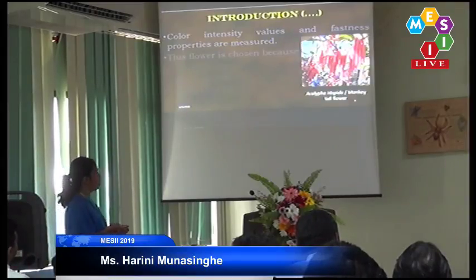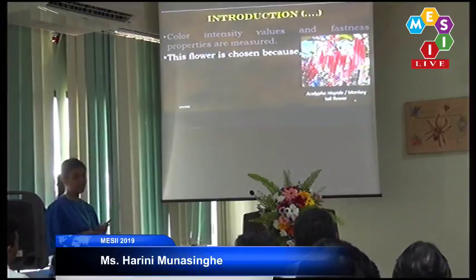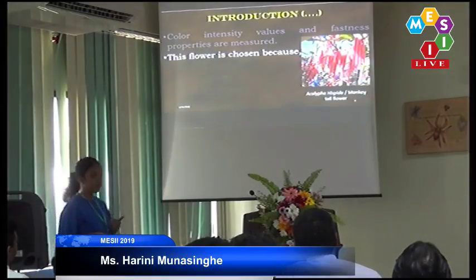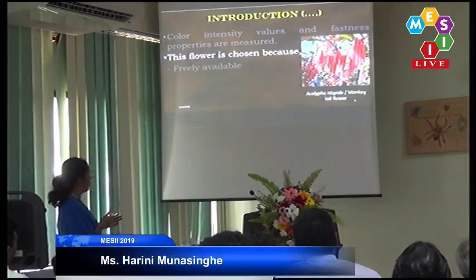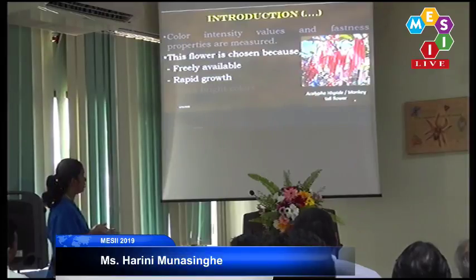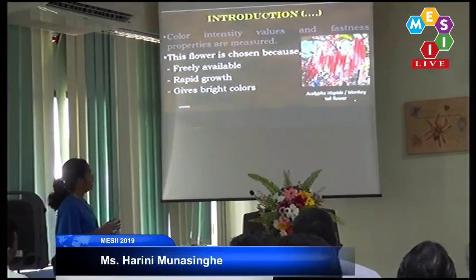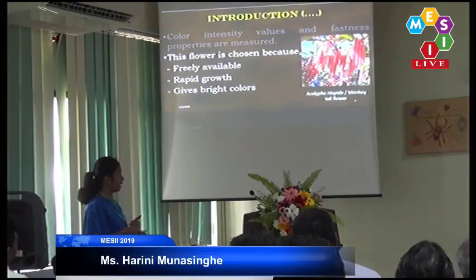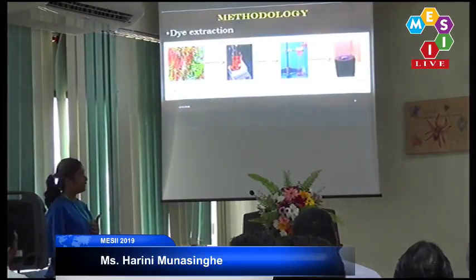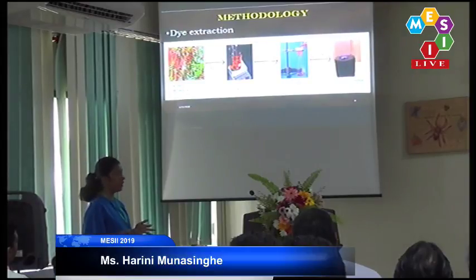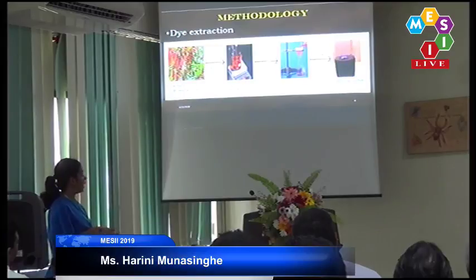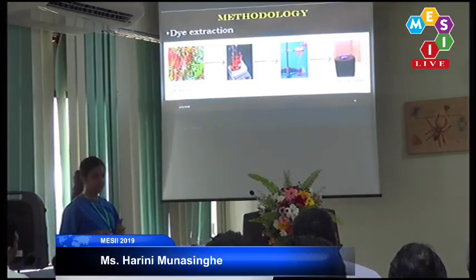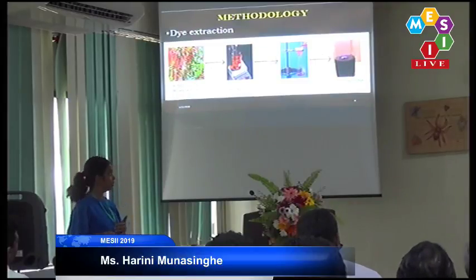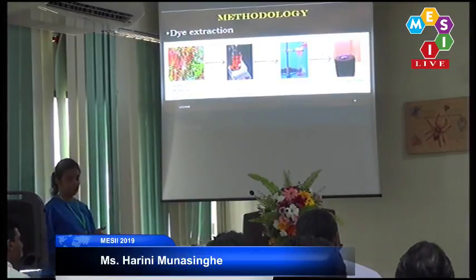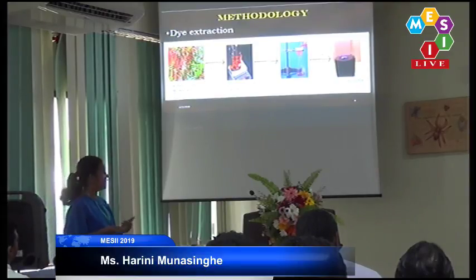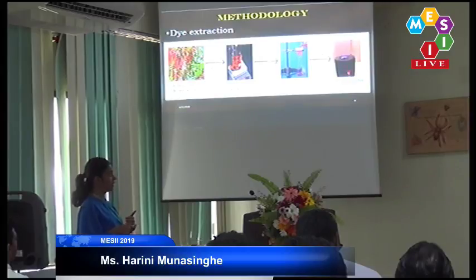In this project, we chose Acalypha hispida, which is generally known as monkey tail flower, to extract the dye. And also we chose this flower because it's freely available, has rapid growth and gives bright colors. After finding the best natural source to extract the dye, we did the dye extraction process. The dye extraction process was done under a simple aqueous extraction method. Here we cut these flowers into small pieces and the dye extraction was carried out using water as the solvent at 100 Celsius for 2 hours, and the solution was filtered